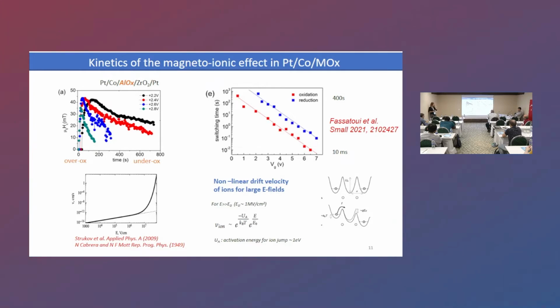Okay, so as I said, the switching time can be changed considerably by increasing the voltage because of this exponential variation of the switching. That is related to the exponential variation of the drift velocity of ions within the dielectric layer. This was predicted theoretically a long time ago by Mott, and it is also explained in this paper.